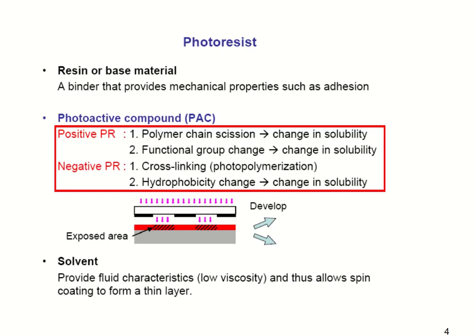By exposure to UV light, the positive photoresist's polymer chain is disconnected, or its functional group is changed. In that way, the exposed photoresist becomes easier to remove. That's how the positive photoresist works. On the other hand, for the negative photoresist there are also two kinds: one is cross-linking, and the other is a hydrophobicity change. By UV exposure, the cross-linking in the exposed area is enhanced, so after UV light the negative photoresist becomes hard to remove because of this cross-linking. Hydrophobicity change works similarly.